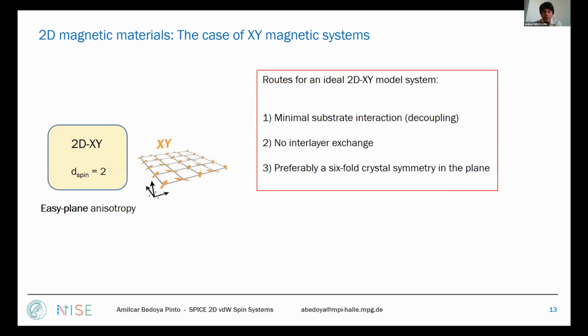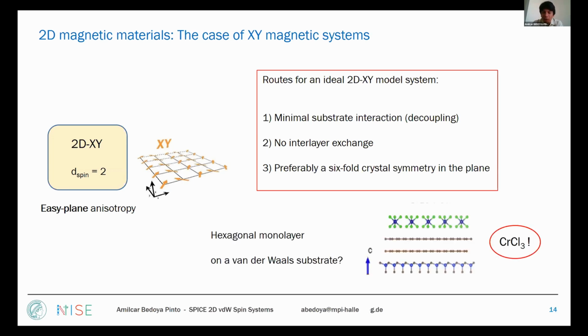So in summary for this introduction, the route to get an ideal 2D XY model system would be a minimal substrate interaction, that means a decoupling from your crystalline substrate. Of course, no interlayer exchange, that means you have to assess that you are really in the 2D limit. And if you have a crystalline material, you will prefer a sixfold crystal symmetry in the plane to have the least possible perturbation to the XY model. And that's how we came to the motivation for this study. All these three conditions will be fulfilled if we can prepare a hexagonal monolayer on a van der Waals substrate.